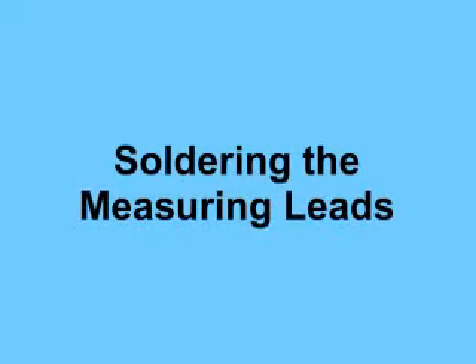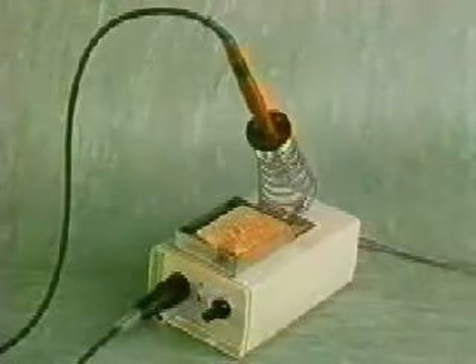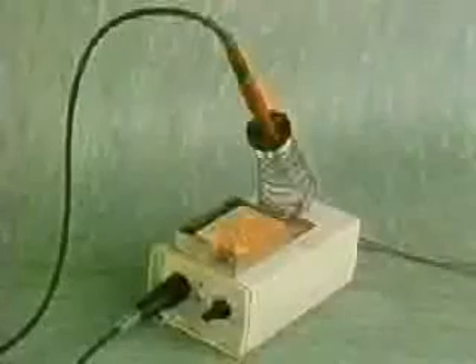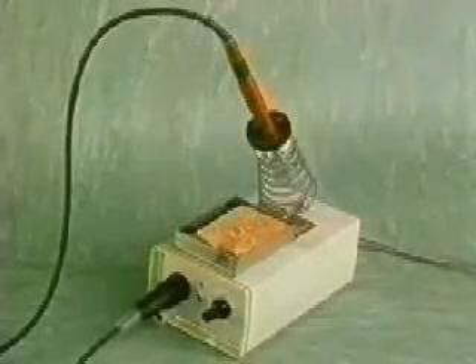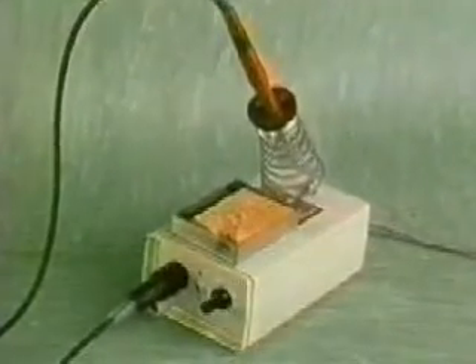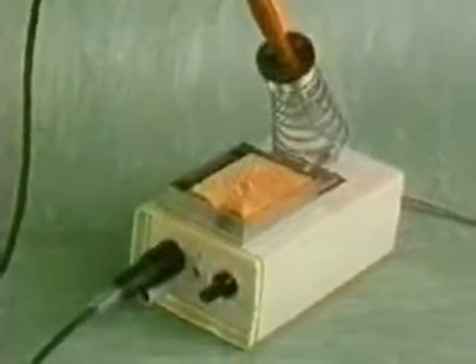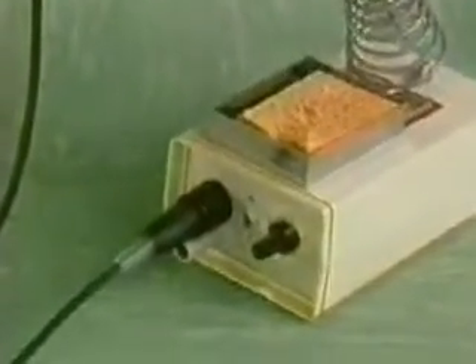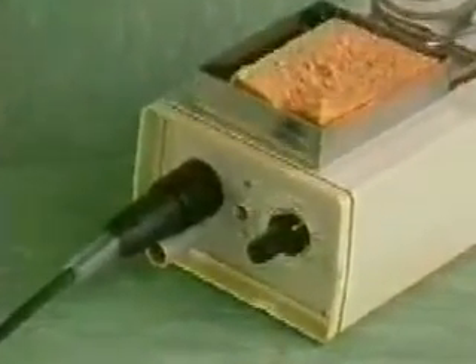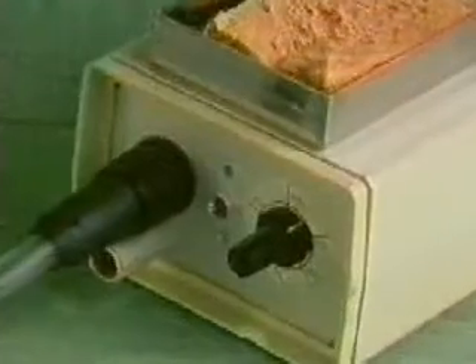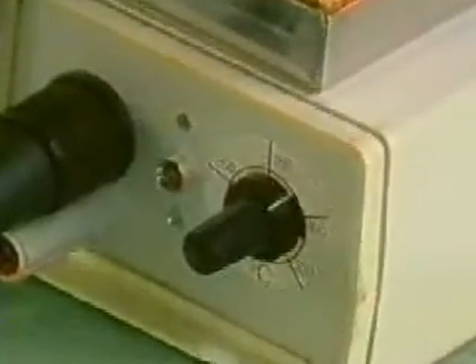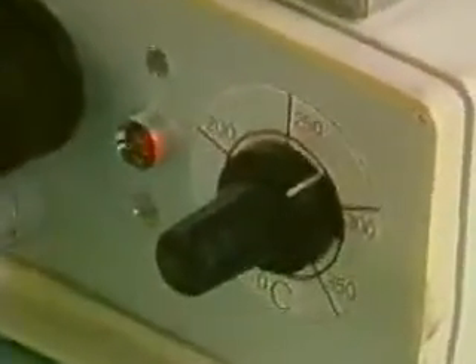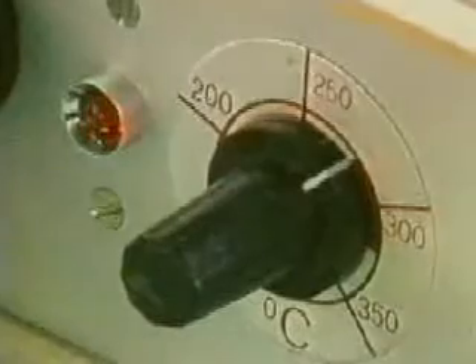Soldering the measuring leads. When carrying out soldering on the strain gauge, a soldering station with temperature control is a great advantage. Make sure that the soldering iron temperature is set correctly. A temperature of about 250 to 270 degrees centigrade is required for the solder used here, which has a pure colophonium core.